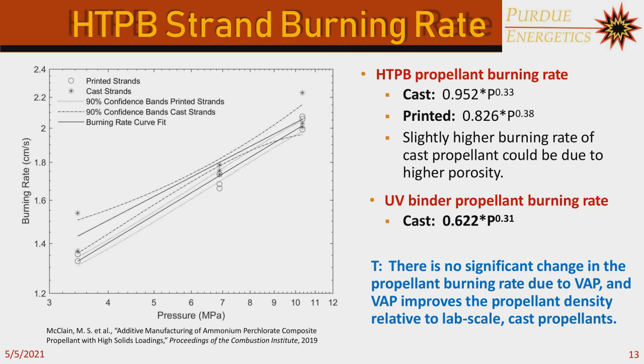We also looked at the burning rate of the UV-curable propellants, and what we found is that although the slope was relatively the same, the burning rates were overall shifted downward, so they were less. So the trade-off is that although you can cure quickly with this UV-curable epoxy, it won't necessarily burn as well as HTPB. But in general, the overall takeaway from the study is that we didn't see any significant changes in the burning rate from VAP, which is good. So we didn't really lose anything here. And we actually saw a slight improvement in the densities of our parts when we compare it to small-scale casting.